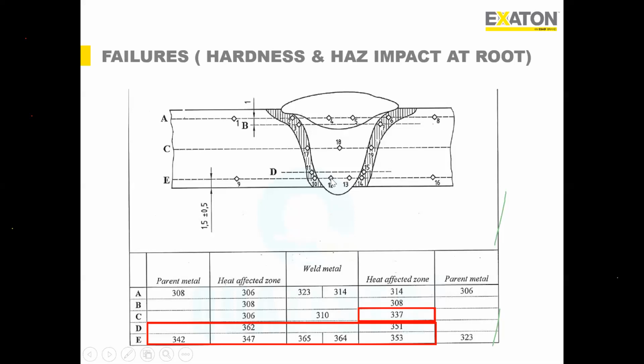You see here the number E, which is the root side, 1.5 to 2 millimeter from here. The point on the weld metal goes to 365, 364 HV, and the heat affected zone was 353. The parent metal has also been affected, we got 342. So by using this super duplex, with multiple layers and slow heat treatment, we got basically some sort of secondary austenite there, and the hardness was very high. So when the hardness was very high, naturally the impact value fell on the root side.